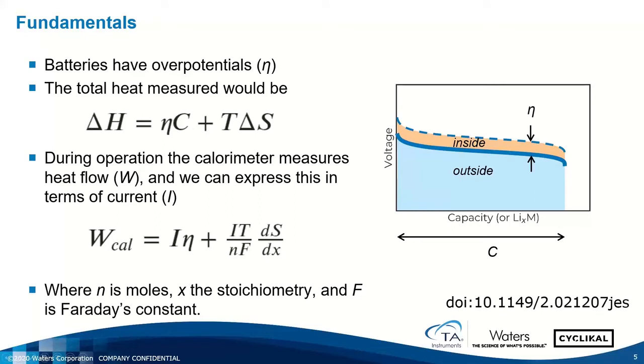But when we're operating the calorimeter, what we're actually measuring is heat flow, right? So watts. And so we can express this equation in terms of current. And so here we have current times overpotential, which, current times voltage, gives watts. So we have a power for the heat dissipated because of the overpotential. And then we have our expression for entropy expressed in terms of current, where we have the change in entropy as a function of the stoichiometry of the material, and then related to the current by the number of moles of lithium, since there's 1 electron per lithium. And so this X here corresponds to the X in the stoichiometry of the material. So as the material is being either lithiated or delithiated, this entropy is a function of the stoichiometry.